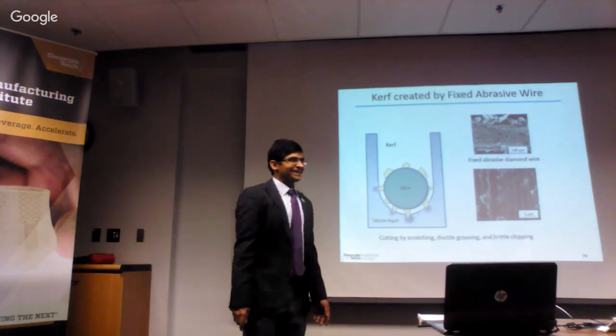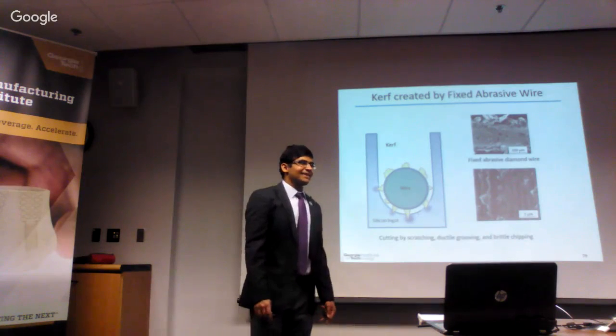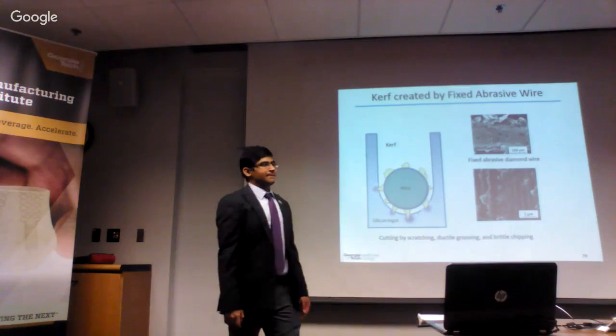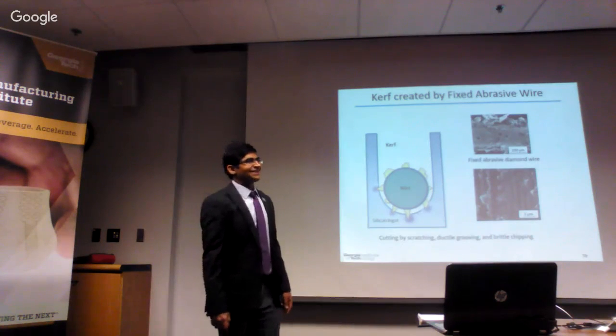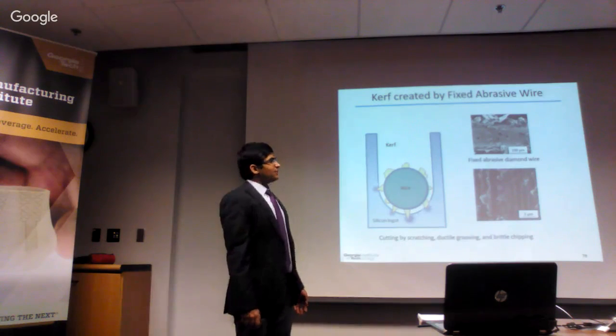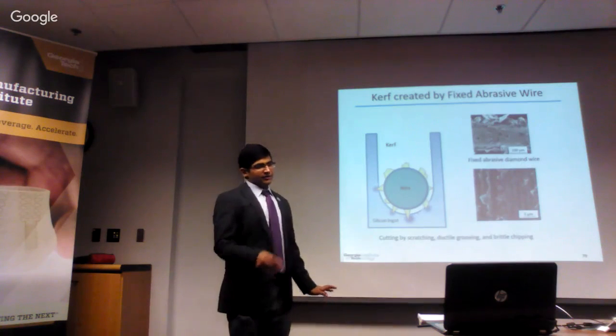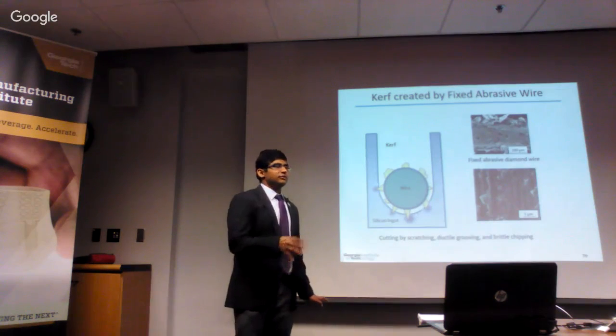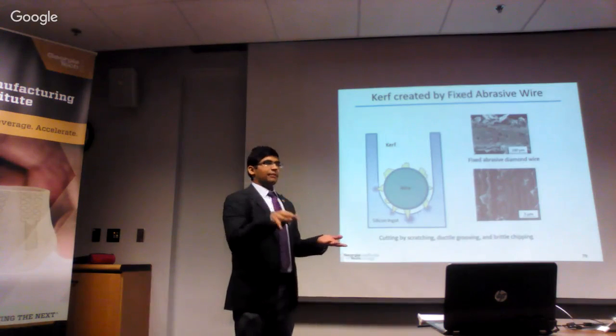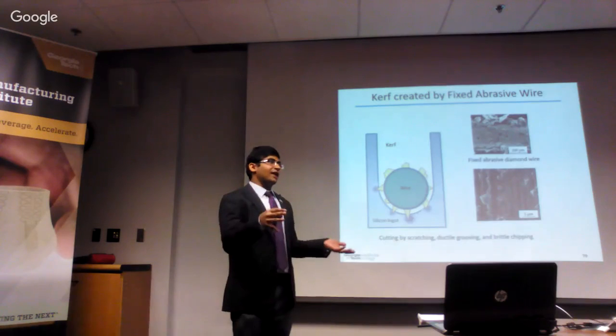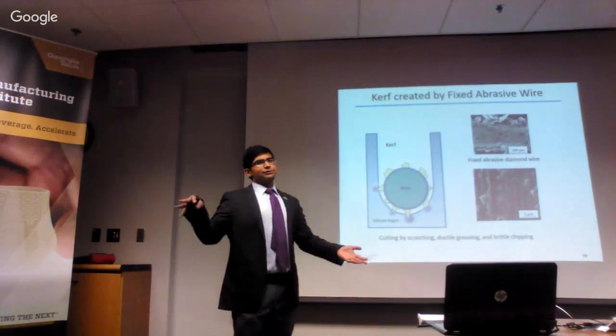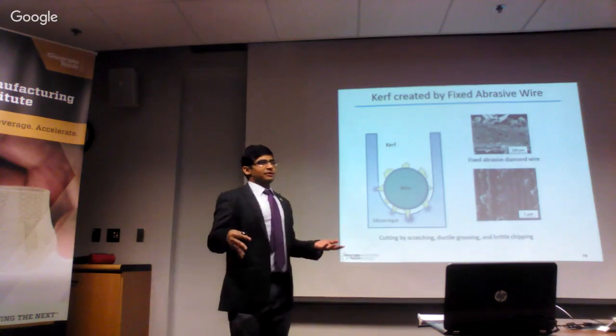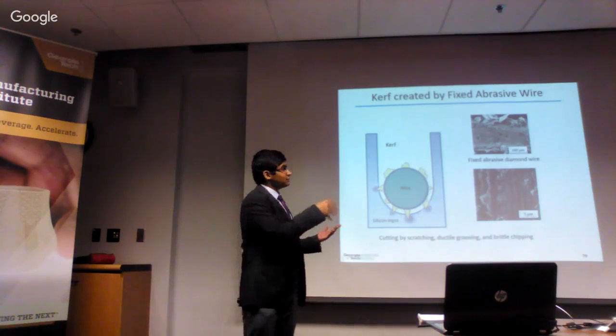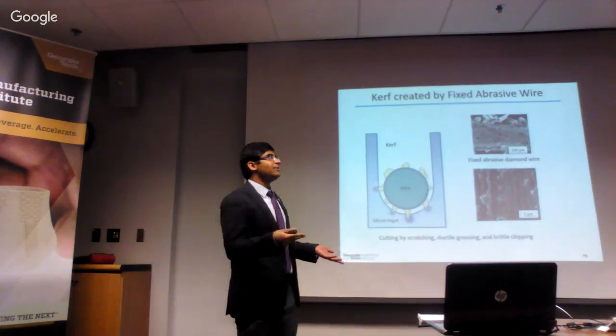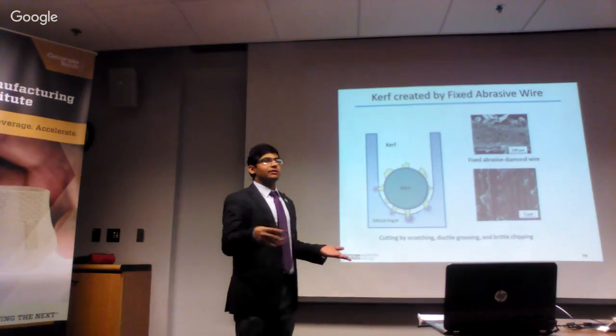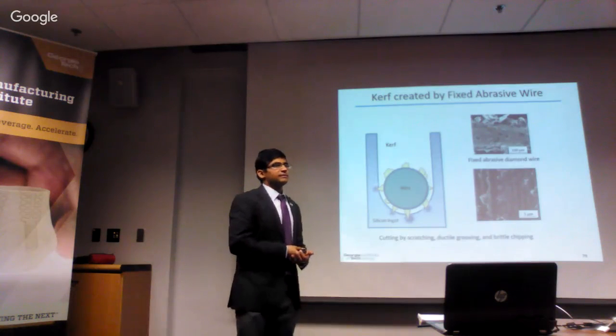That's very helpful. And just as a follow-up, what is the typical post-process after a sawing operation? Is there planarization or polish that removes these cracks? So the typical process is etching with KOH to remove the damage, and the damage removal is as much as the crack depth. The damage removal used to be around 40-50 microns earlier, but with recent advances in abrasive shape with our manufacturer feedback, we found they now only remove 5 to 10 microns of damage by that chemical. Okay, so it's getting on the order of the crack length. Yes.